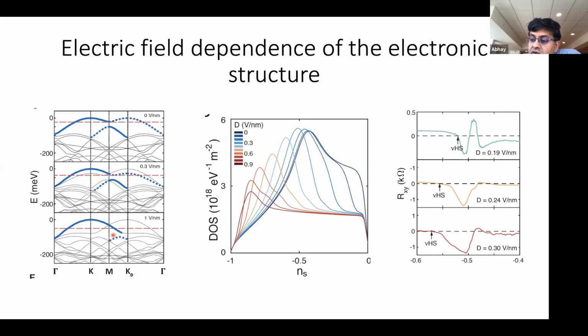So in transport, if you look at twisted bilayer graphene, there is one work from Pablo, which is looking at the superconducting state and the anisotropy of HC2, which they find shows some anisotropy. So that's the transport evidence for nematic behavior. In twisted double bilayer graphene, there's no evidence so far, but we are actually trying to do experiments. What you would want to do is measure the resistance along the two different directions and see how that changes. And in the ideal circumstance, you want to do something like the beautiful work of Ian Fisher, where you apply some strain and look at the response. That's something we are trying to do. But these things can be quite a delicate signature in transport, right? Yes, these guys are very special that way.